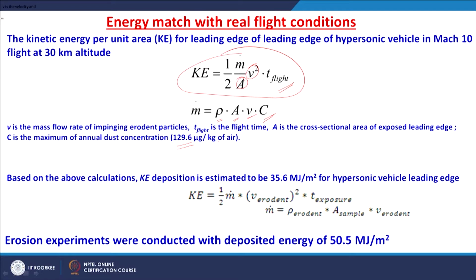Based on the above calculations, the kinetic energy deposition estimated for the hypersonic vehicle leading edge is around 35.6 megajoules per meter square. The kinetic energy we know is given by half m dot v squared times T of exposure. So, we know the mass flow rate of the impinging particle, the time of exposure in the test, and then we know the density of this erodent and the sample cross sectional area.